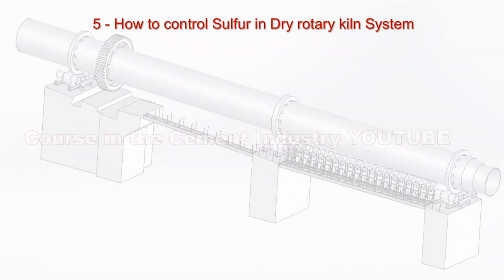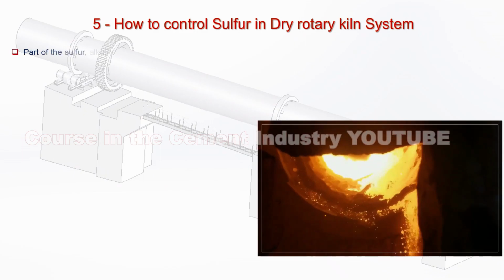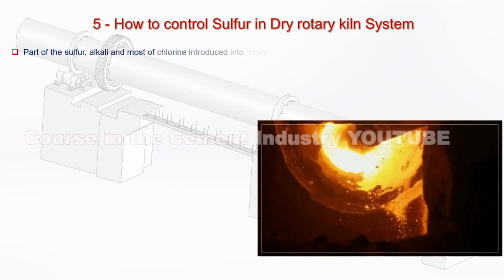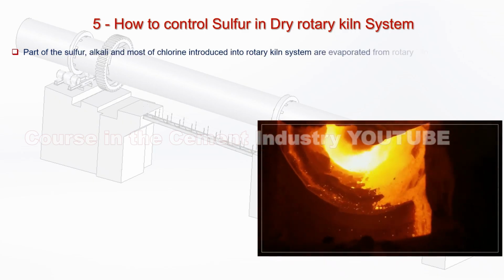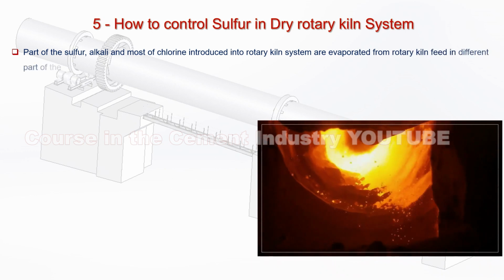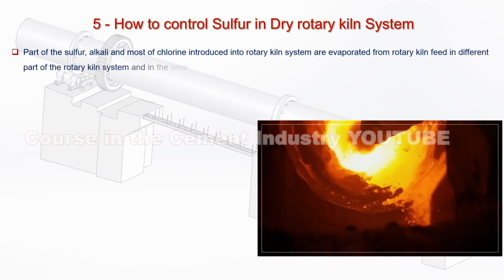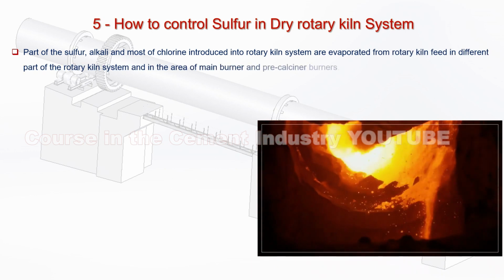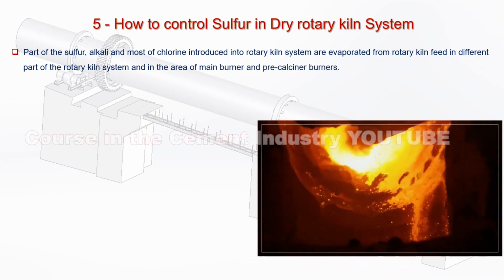5. How to control sulfur in dry rotary kiln system. 1. Part of the sulfur, alkali and most of chlorine introduced into rotary kiln system are evaporated from rotary kiln feed in different parts of the rotary kiln system, and in the area of main burner and precalciner burners.